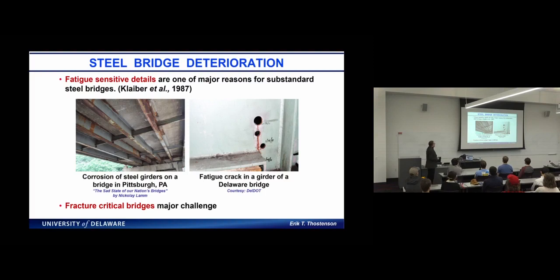Okay, so again, this is just an example of steel bridge deterioration. We can get corrosion. I've now, when I've been collaborating, I know that a lot of our bridges have a lot of fatigue cracks, a lot of them. And in fact, this is a fatigue crack in a girder that is not too far away from campus, and this goes over an interstate highway. And what they've done here is they've drilled what's called a crack stop hole. So that blunts the crack tip, so that reduces the stress concentration of the crack.